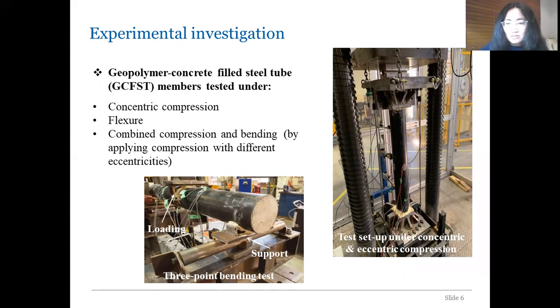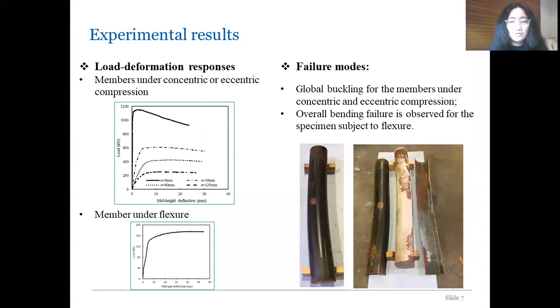The test on the concentric and eccentric compression was performed using the setup on the right-hand side. Each member was tested under pin end conditions, and we used LVDTs and strain gauges to trace the deformation responses of the structure when the load was increased and decreased through displacement control. Due to the time limit of this presentation, I just wish to show some key results and observations from the